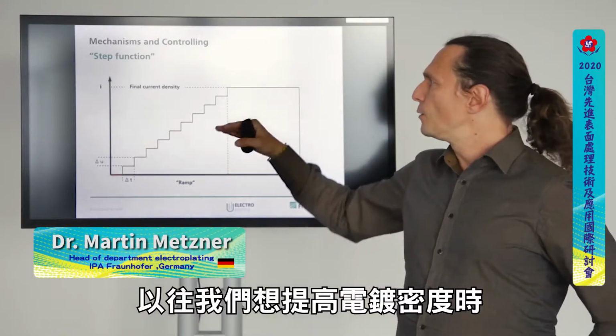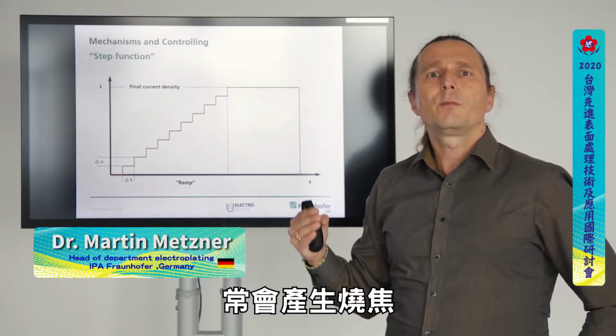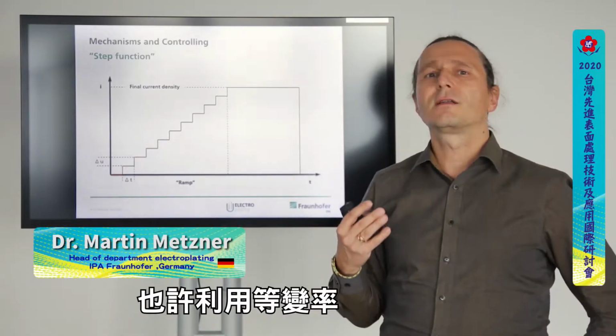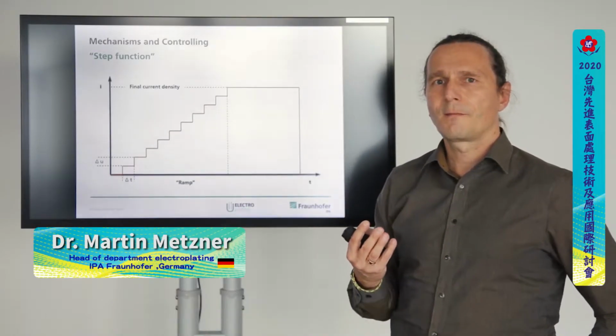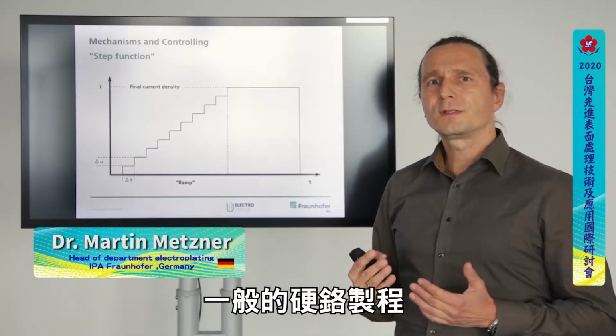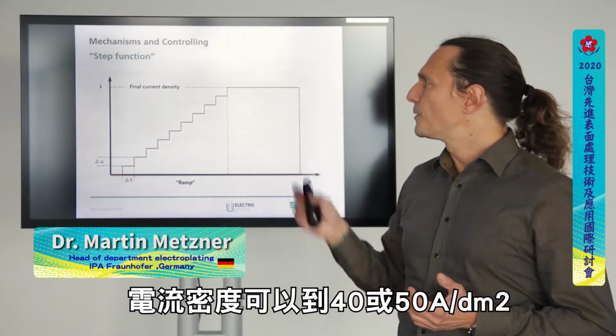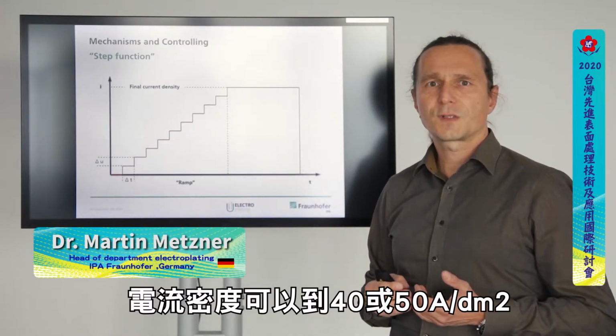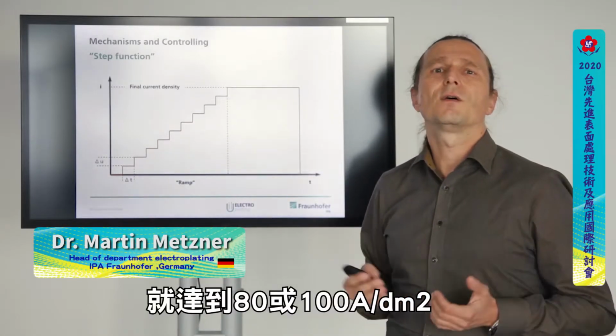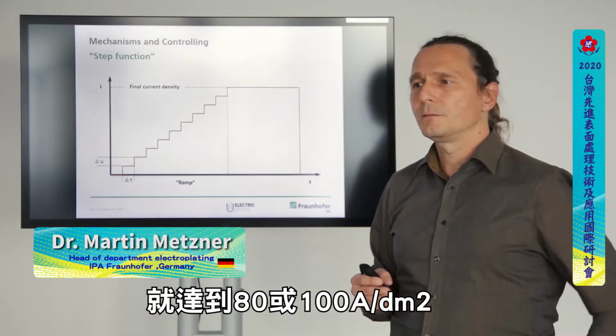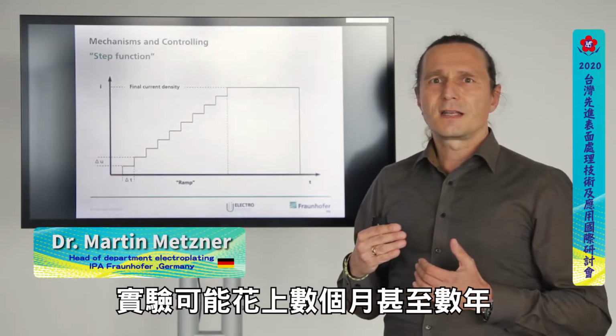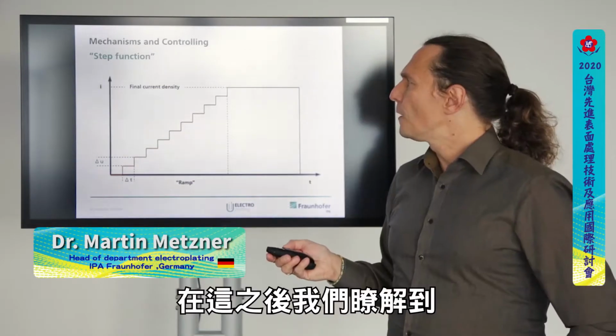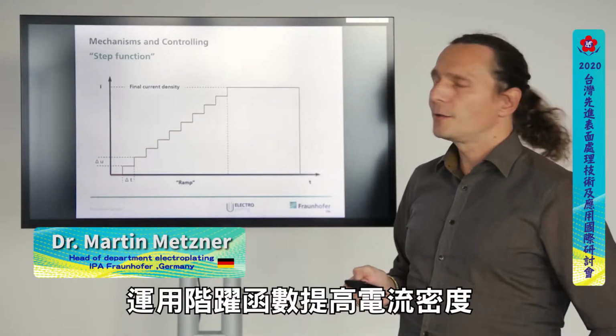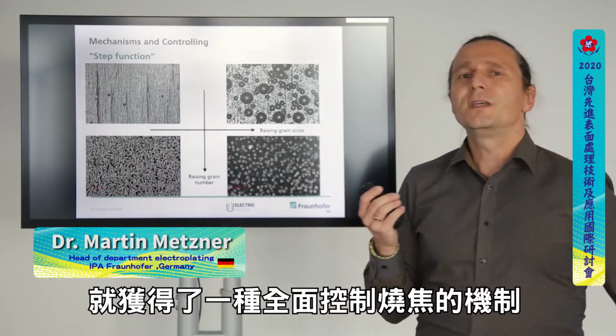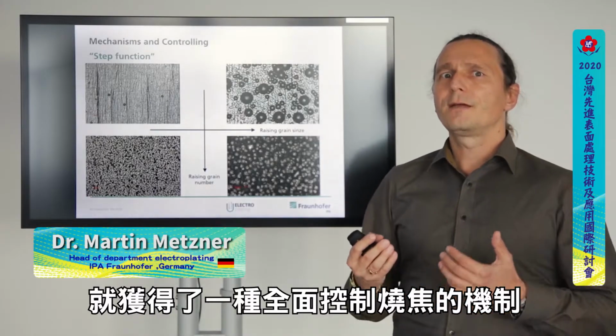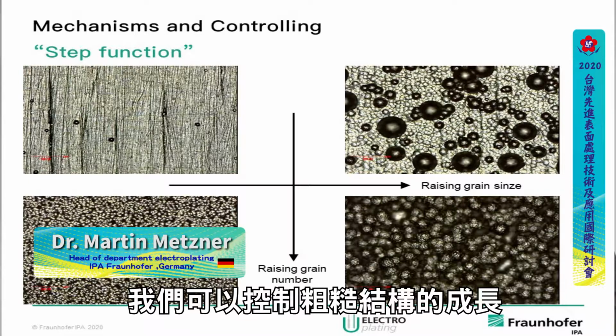We thought about what happens when we go to a higher level of current density, where we normally get into burning, and maybe with this ramp we can learn to control the burning in some way. When we talk about the normal hard chromium process, we've got 50 degrees of electrolyte temperature, and we go up to a current density of something like 40 or 50 amperes per square decimeter. In the first trials we went up to 80 or 100 amps per square decimeter. This is a very short summary now. We talk about experiments that lasted for months or, to be honest, years. After all that, we learned that when we play around with the step function with a higher current density and a lower electrolyte temperature, we have a mechanism where we can control the burning. So we can control the growing of rough structures.